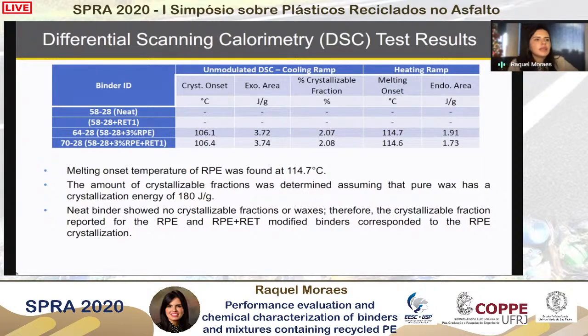So we can see here from the DSC results that when we have the neat binder by itself and the binder modified with the terpolymer only, we could not detect any wax content or crystallizable fractions in the material. And then when we have the addition of the recycled plastics, we see an increase by 2%.